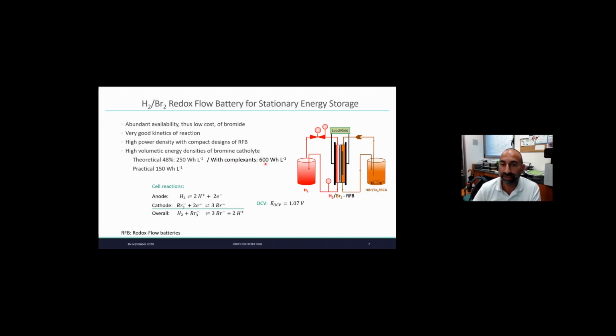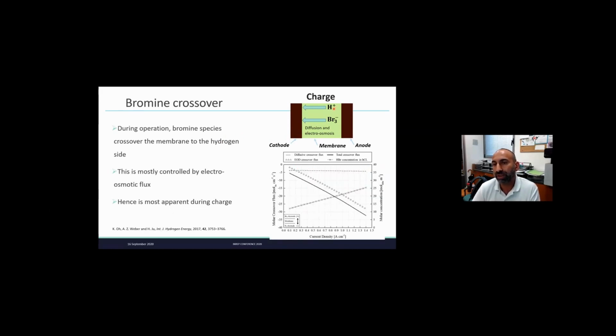So even if we can reach very high energy density, and the density can be very, very high if you had some complexants, up to 600 watt hour per liter, which is fantastic, in that case you have a real issue with the corrosion of the catalyst. Why? Because when you're charging your battery, you have some protons that are transported from the anode to the cathode, and together they bring also some tribromide, okay? Because you have some association of the ions.